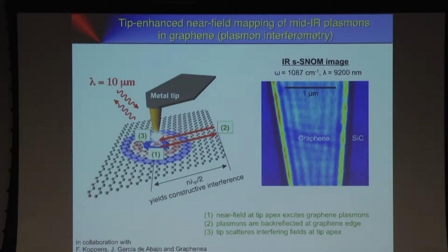So here our microscope comes into play. We now use this near-field focus created by the metal antenna here to do both, to excite and to image these waves. And the idea is as follows. We take the tip, place it on top of the graphene sheet. We shine 10 micrometer wavelengths on the tip. We create this nanofocus. Now, if you think of this in terms of momentum distribution in this focus, we will have a lot of near-field components with a very high momentum because we are deep sub-wavelength scale. And there are components with a momentum that match that of the graphene plasmons here. Then the graphene plasmon propagates away. This is kind of a point source, like throwing a stone into water. These waves would propagate away from the tip. So that's the way we excite them.